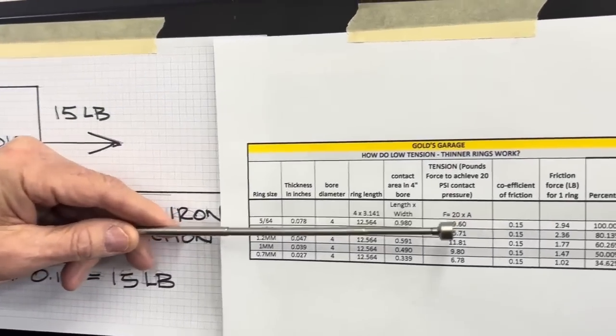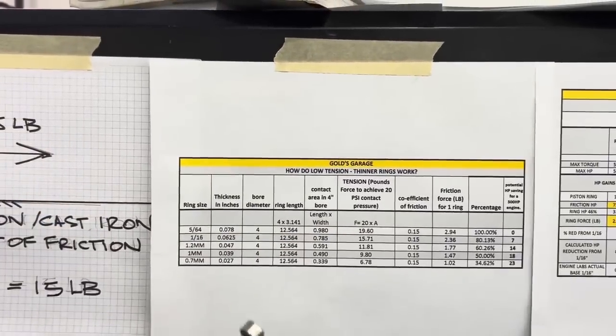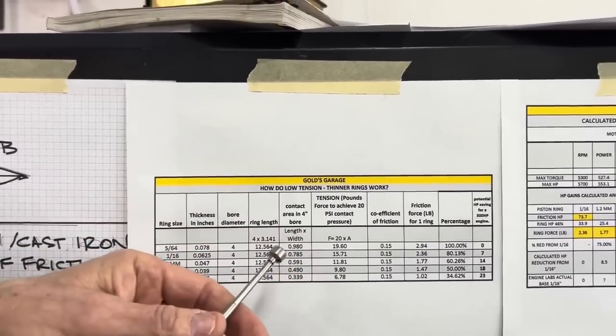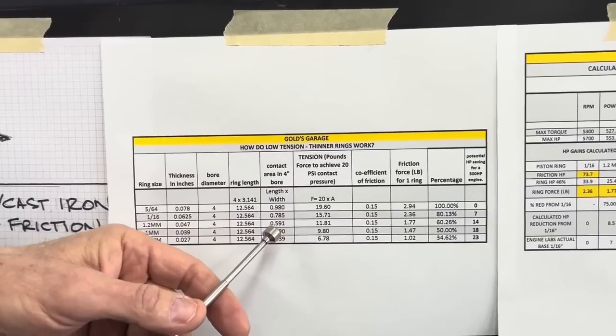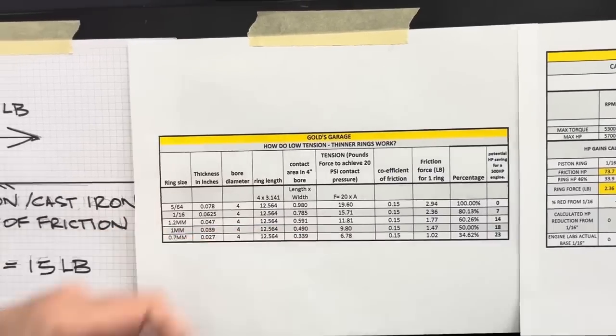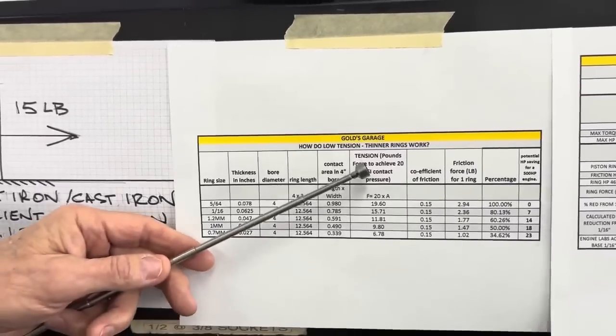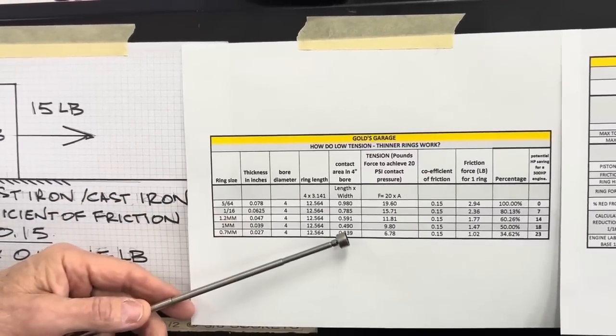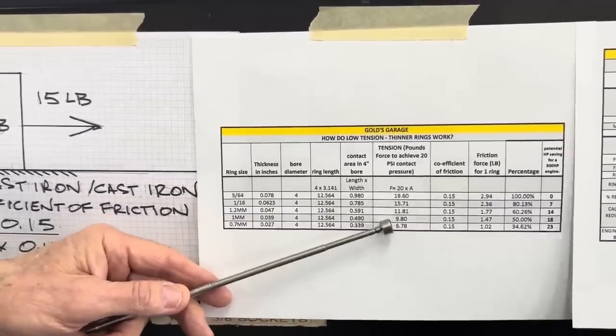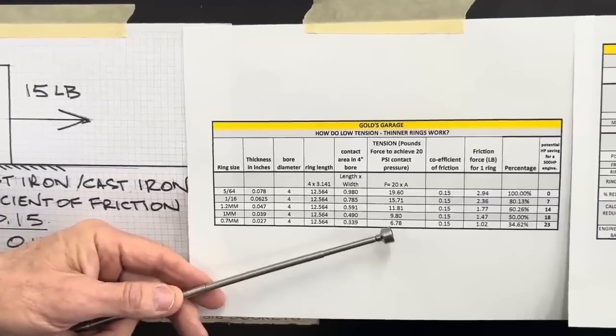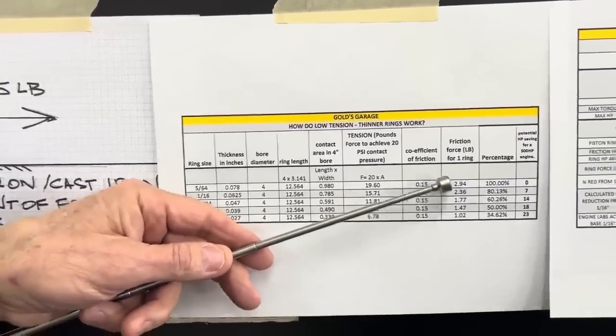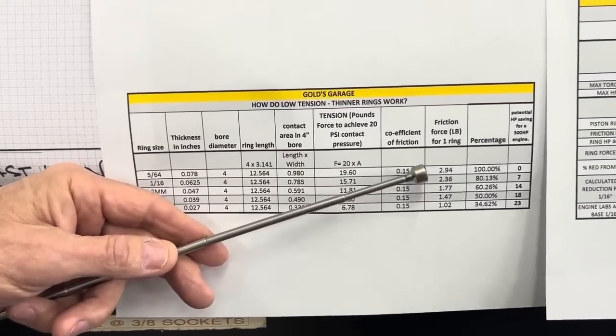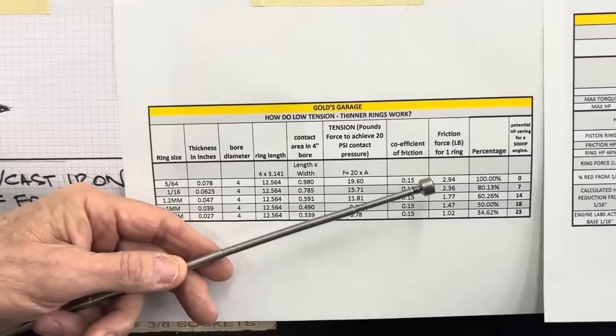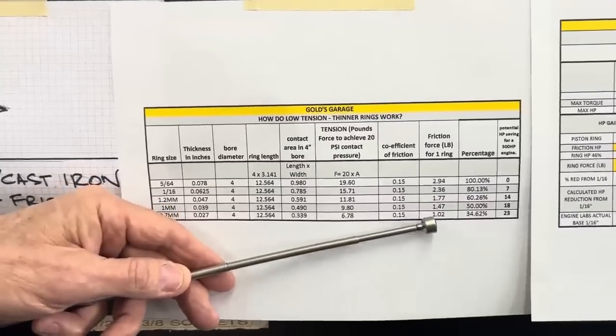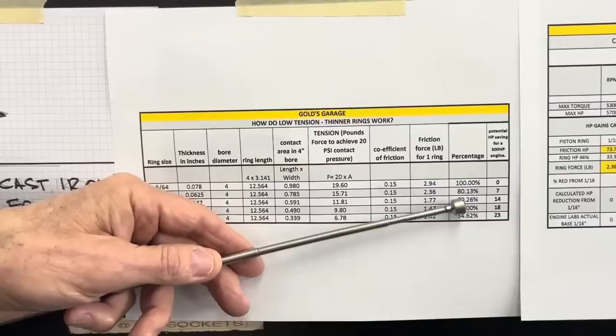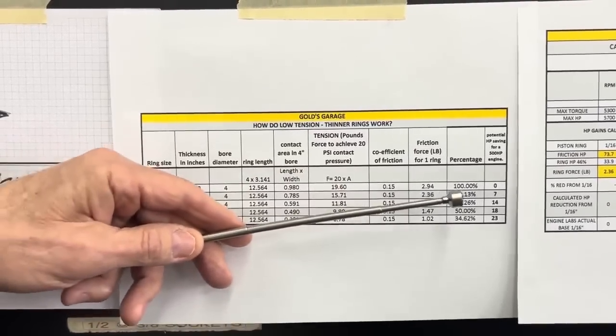That's the difference. So if you have less square inches, here's the area of a 5/64 is 0.980, 1/16 is 0.785, 1.2 millimeter is 0.591, and so on. So the area of the piston ring in contact with the cylinder wall becomes less and less. If the tension equals pounds per square inch, and you have less square inches, then you need less pounds. That converts back to the number of pounds of tension on the cylinder wall to achieve 20 psi times the coefficient of friction. And this is my calculated forces, the actual friction force of one piston ring in a cylinder. So the stock ring is 2.94, and as it gets thinner and thinner, a 0.7 ring is only 1.02. I convert that to a percentage, and then just using the math, I calculated how much horsepower you could gain.